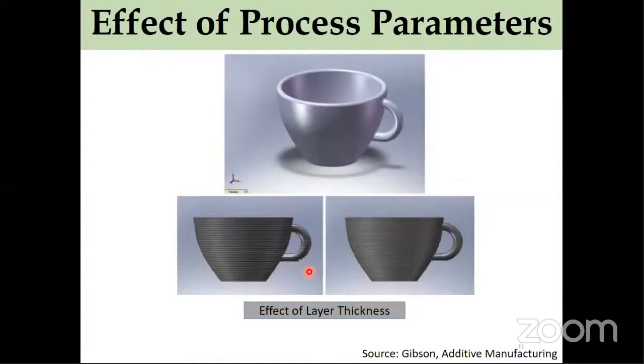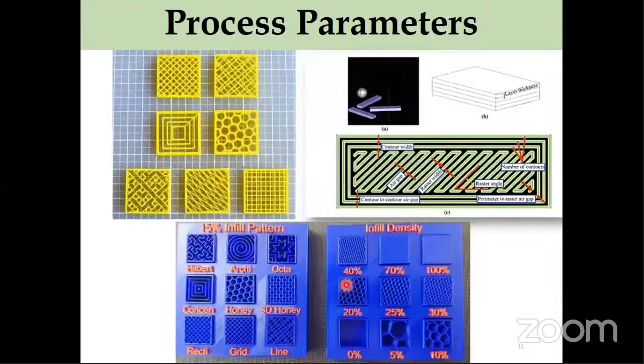This is basically the effect of layer thickness. If you increase the layer thickness, you will see that a part which is printed would be rough like this. But if you want a smoother part and you want to capture the geometry very perfectly, then you have to decrease the layer thickness. So this is how a small variation in the layer thickness will actually vary the part quality.